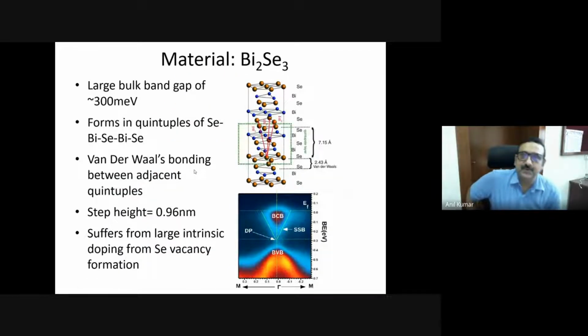The material I'm going to talk about to start with is bismuth selenide, Bi2Se3. The structure of Bi2Se3 is given here, and it consists of several quintuple layers. Adjacent layers are connected by a van der Waals interaction, so you can break the layers and exfoliate them. Typically a unit cell is less than a nanometer, and each layer corresponds to approximately 1 nanometer. You can have multilayers, exfoliate them, and make devices according to your convenience.